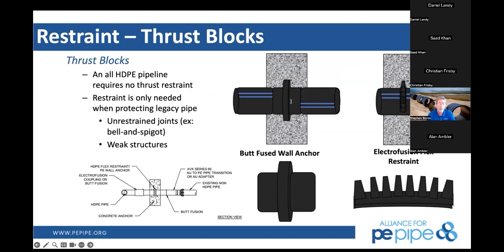And then you also have traditional anchor blocks. So if I need to anchor it, polyethylene, as Assad mentioned earlier, has a little bit higher thermal expansion coefficient. The nice part about it is it's pretty easy to mitigate any movement, and there's ways to do it. You can use a butt fuse wall anchor in an anchor block situation. You can use an electrofusion flex restraint that you can put a number of around the diameter of the pipe, depending on how much pull out you're looking for in design. Encase that in an anchor block design, and that will fully mitigate any type of movement when you connect that to a valve housing or wherever it might be, and not have any issue with the moving of the pipe.